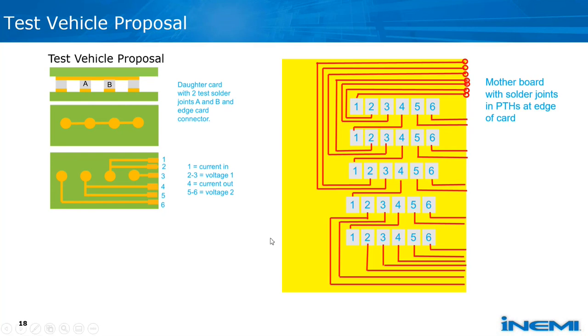So this is the test vehicle cross section. On the left here, the top first green bar, and underneath it is what we call the package substrate. And that is attached to the daughter card. The two joints that will be studied for electromigration are A and B. The section below those two is the design for a 4-point test for measuring the current while applying voltage, and that was designed by PJ. Each daughter card will have two test solder joints, and it will have a card edge connector.